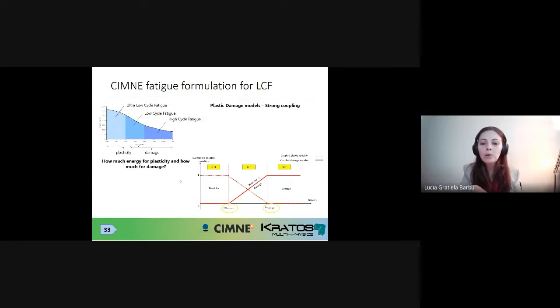But what happens when you are interested in migrating, for instance, from low cycle fatigue to high cycle fatigue? You had some plasticity at the beginning, but then you are going towards a load history which only needs to give damage behavior inside your model. Well, if you're using a weakly coupled model, you won't be able to do this because if you stop plasticity, automatically this stops damage. So this is why we needed strong coupling, why we needed to integrate damage and plasticity at the same time, and we needed models which would be easily reduced to each one of the base phenomena, either reduced to plasticity, either reduced to damage if needed.